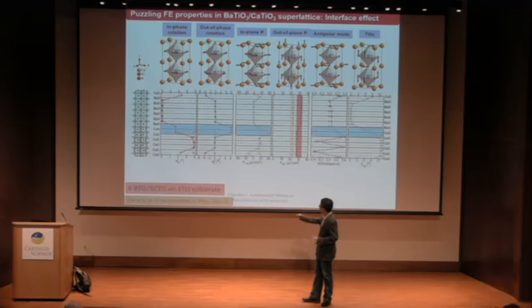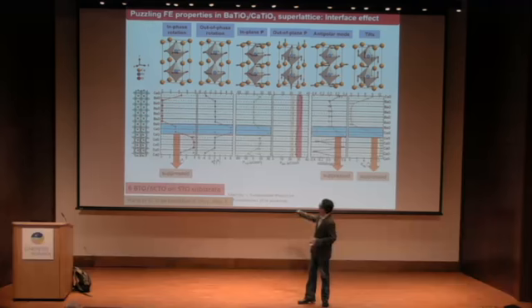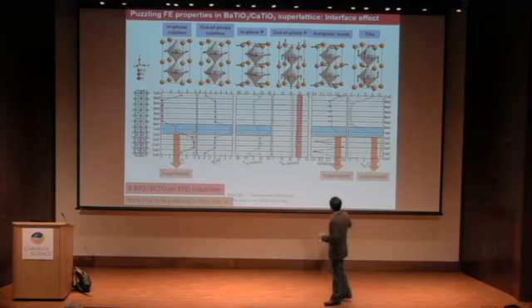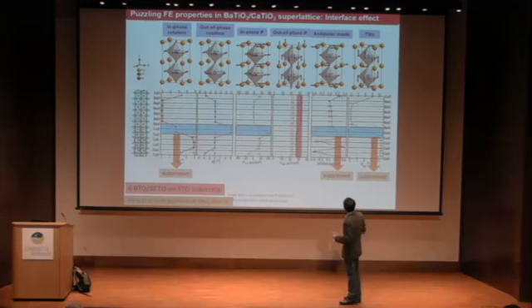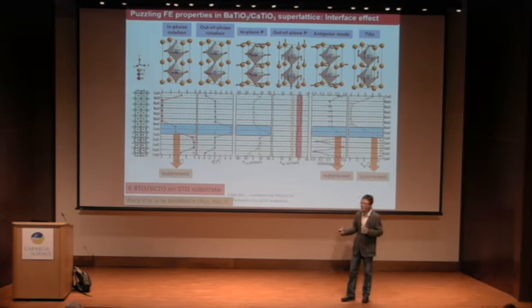At the interface, we look at the interface region in blue. What do we see? We see a suppressed in-phase rotation. We also see a suppressed tilting mode. Because this is so suppressed, we expect the antipolar modes are also suppressed.